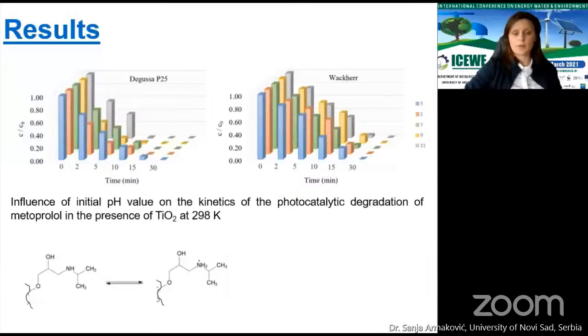Obtained results of metoprolol degradation with the changes of pH can be explained through consideration of the surface charge of the catalyst and the pK of metoprolol. The pK for metoprolol is 9.7. When the pH is lower than the isoelectric point of the catalyst, the surface is positively charged, and anions are attracted while the cations are repelled. Metoprolol contains an amino group. When pH is less than pK, the condition is fulfilled for its protonation.